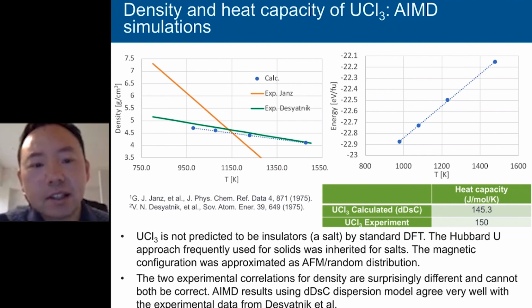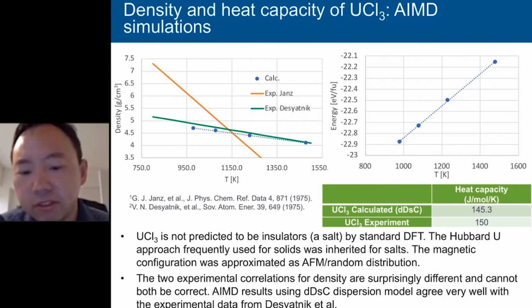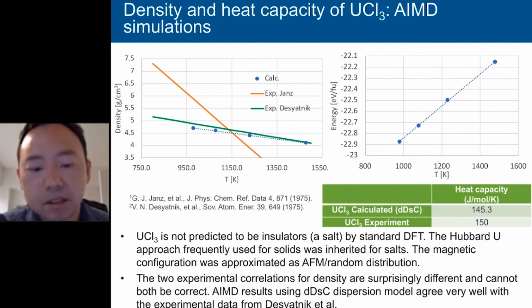You can immediately see that there are two sets of experimental data. One is shown as the green line, and one is shown as the orange line, I think. These two experimental correlations are surprisingly different, and they cannot both be correct. There's a huge discrepancy between these two, and Ab-Initio MD agrees much better with one of the sets, as you can see on the left figure. So this is where the Ab-Initio MD can be used to judge the quality of experimental data if there exists a high discrepancy.